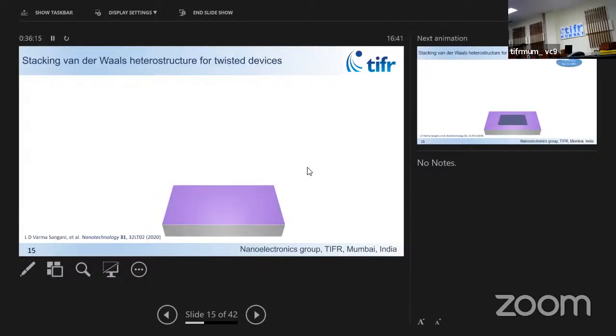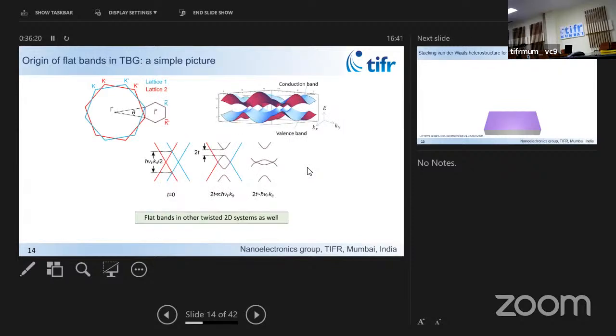And a quick question again, going back to the picture, where does the angle really matter? Because we can also tune the distance, right? Good question. The distance between the two layers is a knob that has been little explored. It's hard to control in experiments. Angle is very easy to do. People have done experiments using hydrostatic pressure. You make this layer, you put it in very high pressures, 100 atmospheres kind of pressure. Then this gap changes, and this hybridization of the bands changes. So it has been verified, of course, but that knob is hard to do in this system.